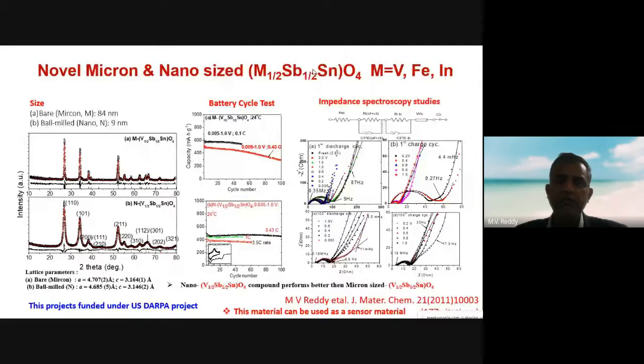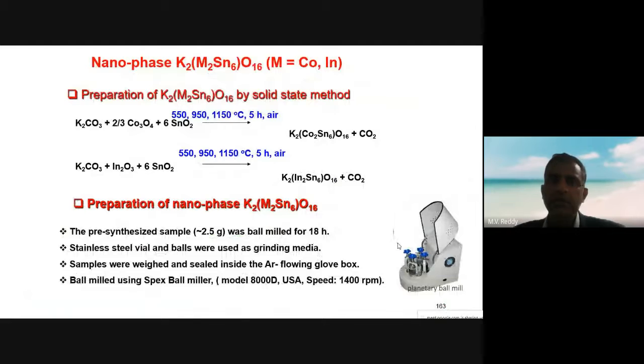Again, the vanadium-based system. You see that with either submicron size or nano size, if it is nanomaterial, we can get reasonably good stability and good current rate capability. If it is submicron, we get slow capacity fading after 50 cycles. We checked the possible reasons again with impedance, and we see minimal variation, especially with vanadium. If you go for other matrix elements, iron and indium, somehow the capacity is slightly lower. So these are a few.